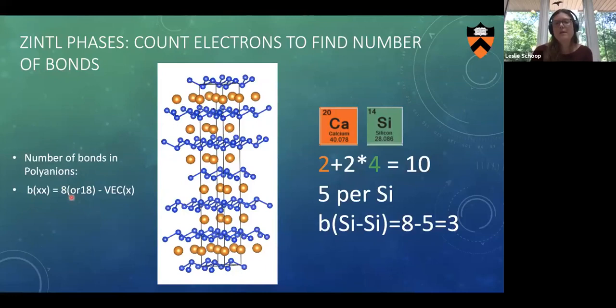So an example is silicon. We said our valence electron count per silicon was 5. So if you subtract 5 from 8, we get a bond order of 3, which means we want to have 3 bonds to have a charge balanced system. So we do have 3 bonds on each silicon, so we're good. It's going to be a simple semiconductor. Okay.